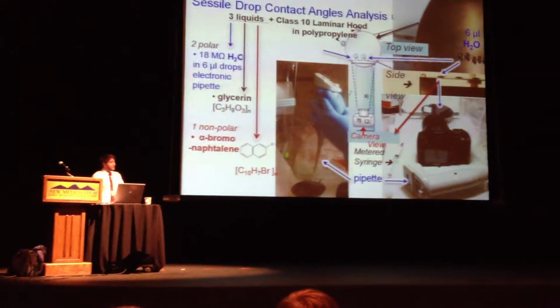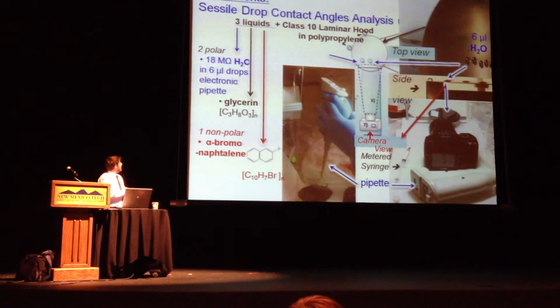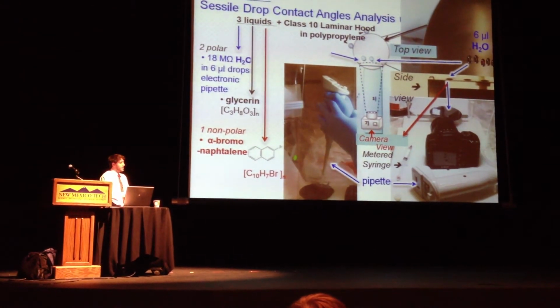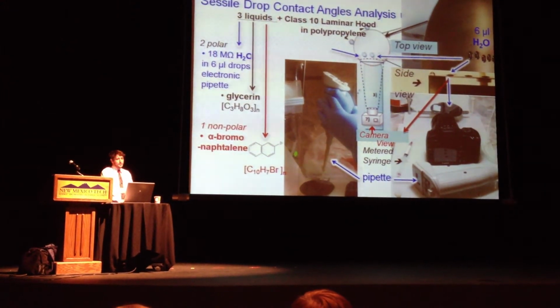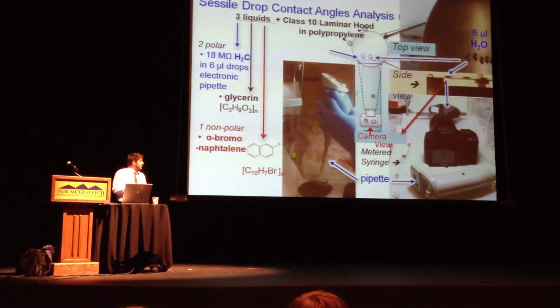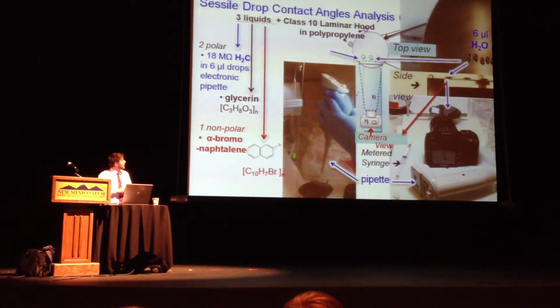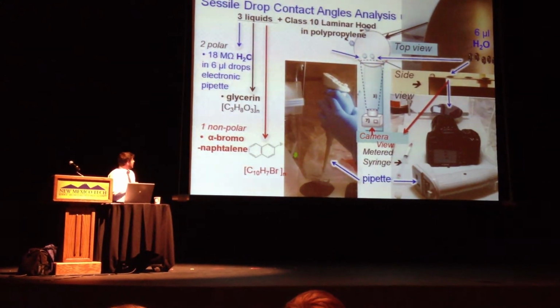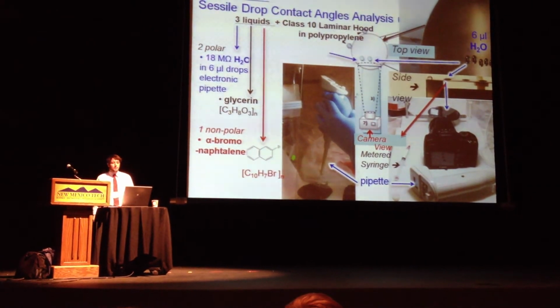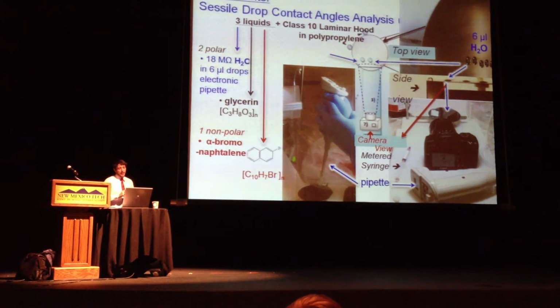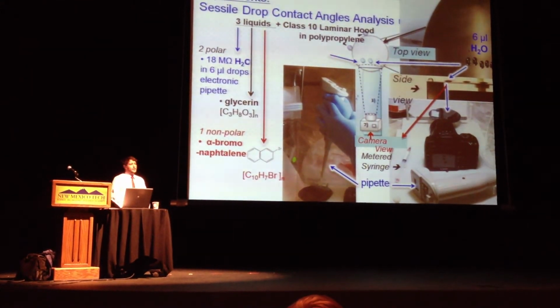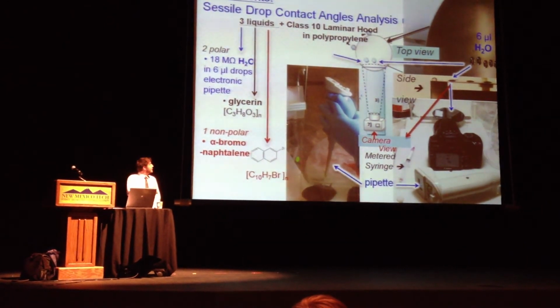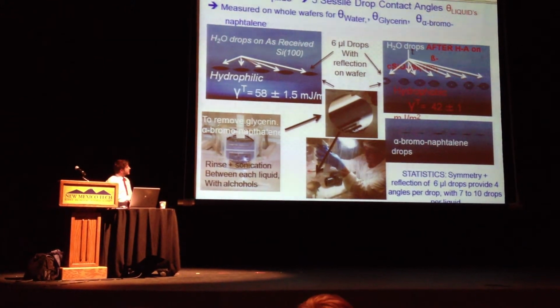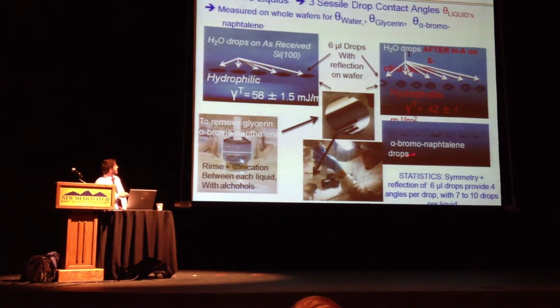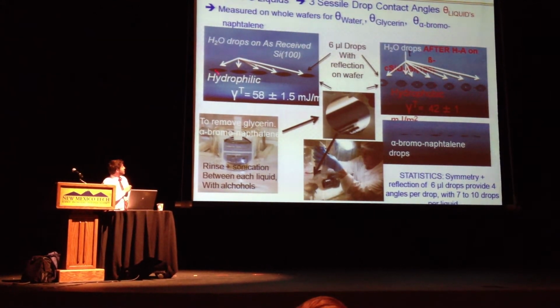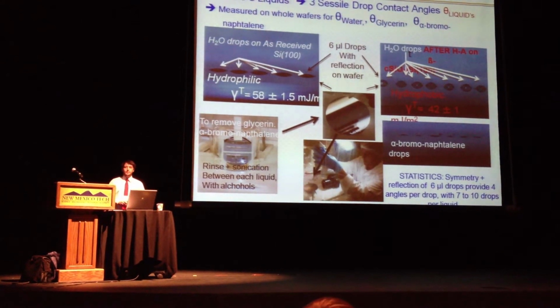Here's a little setup of how we do it, a little bit low tech. We use a pipette to drop our liquids onto the surface with controlled volume to reduce the effect of gravity on the droplet size and the angle. Then we use a camera up close to take images of our droplets on the surface. Our 3 liquids are 18 megaohm DI H2O, glycerin, and alpha-bromonaphthalene, which is our non-polar liquid, which helps us to determine the van der Waals interactions of the surface free energy. What you're seeing here is a reflection of the droplets with the wafer underneath on both sides, and then you have the actual droplet forms up top, and its reflection helps us determine the angle with our goniometry analysis.